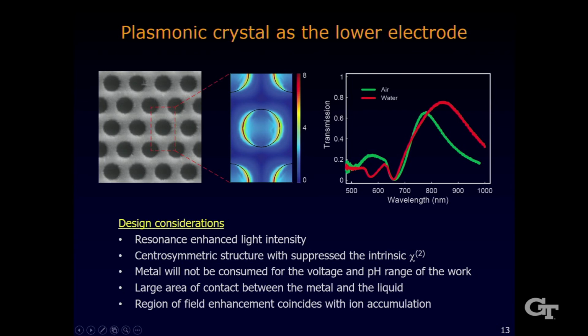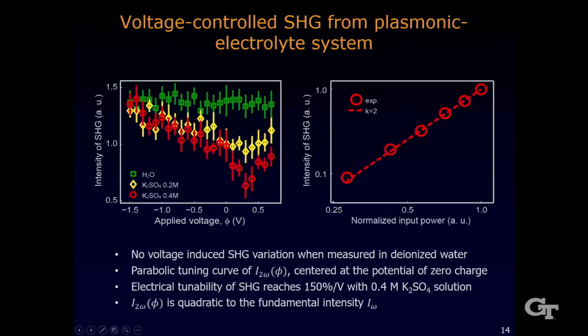This is a pretty hard part because actually, even for gold, if you apply more than positive 2 volt towards the electrode, the gold will disappear, dissolved into the water, okay? Certainly, we prefer to have a large area of contact between metal and the liquid, along with a good amount of field enhancement that overlaps with the ion accumulation when a voltage is applied, okay.